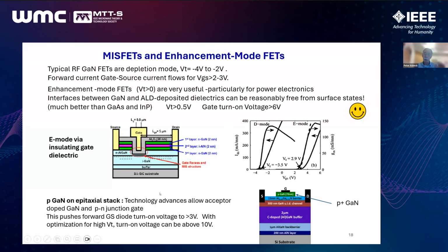I should note that also a more recent development, particularly in the world of power electronics, is that it can form P-type gallium nitride grown on top of it. Then you get a turn-on voltage for the associated PN junction that is very high because of the large band gap of the gallium nitride, and also the fact that you're sandwiching a layer of very wide band gap aluminum gallium nitride between the P and N regions.